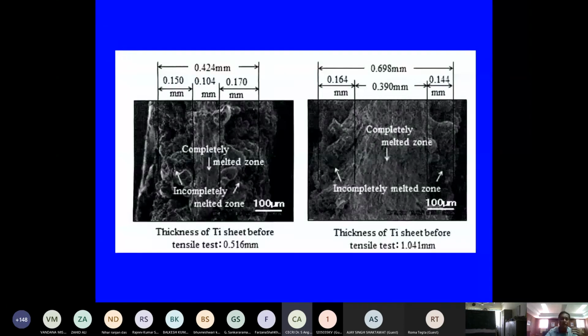Suppose you are trying to develop an implant that is going to be put in the body. These loosely bonded particles should not be on the implant surface, because they will leach out from the implant and deposit in the spleen or some other body part, and it could become cancerous. So we need to be very, very careful while developing this type of implant, and we need to do some kind of post treatment to remove these powders or unmelted or half melted particles from the 3D printed component. I will show a little later how a heat treatment process helps me to get rid of these loosely bonded particles from the surface.